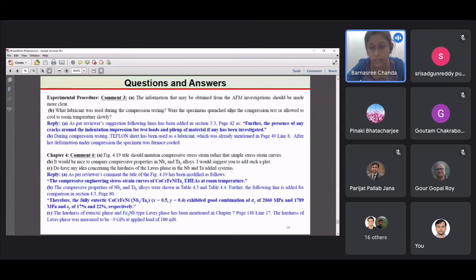So basically, we have done AFM to see if there is any presence of cracks or not. That may show some different result. So we have done AFM to see if there is any pileup or any crack present there or not. That line I have added in my thesis in the experimental procedure. Pileup means the pileup of dislocations, right? Yes, sir. Pileup of material. Okay, pileup of material, and if there are any cracks around the indentation impression.